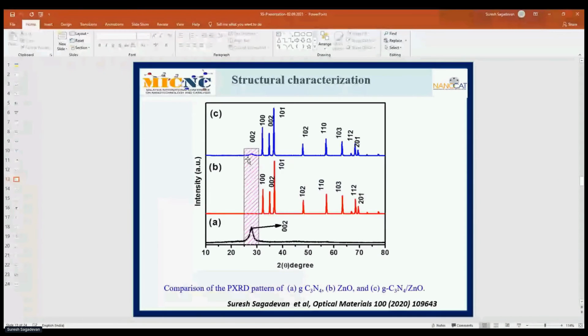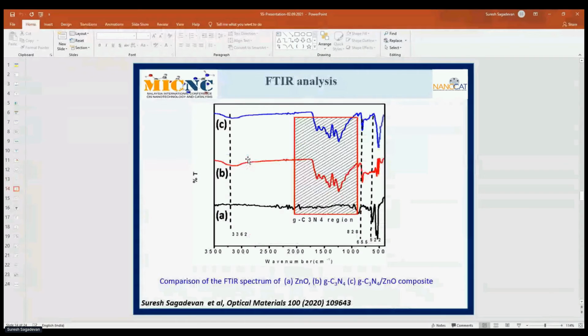So once again, we can confirm this by X-ray diffraction analysis: the graphite carbon nitride incorporated with zinc oxide. And next, we studied the FTIR analysis. You can see figures A, B and C, the comparison of the FTIR spectra of zinc oxide, graphitic carbon nitride, and the composite.